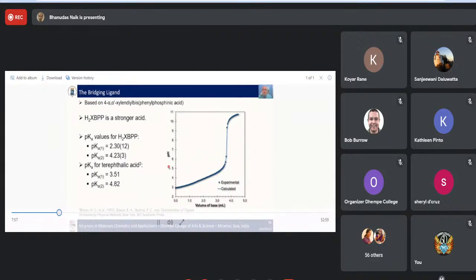The phosphinic acids are slightly stronger than carboxylic acids. My student did a potentiometric titration, so we can actually determine experimentally the pKa values, and you can see that it's 2.3 for the first pKa and 4.2 for the second pKa, which is slightly less than the pKa for the terephthalic acid or BDC.